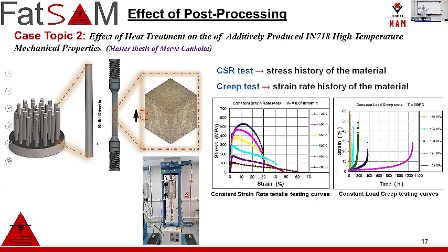A constant strain rate test is actually the stress test of the material. As you know, with increasing temperature, strength decreases and ductility increases. But the creep test not necessarily. As I said before, the most important thing in the creep test is the creep strain or plastic deformation you obtain, or the resistance of the material against creep strain.